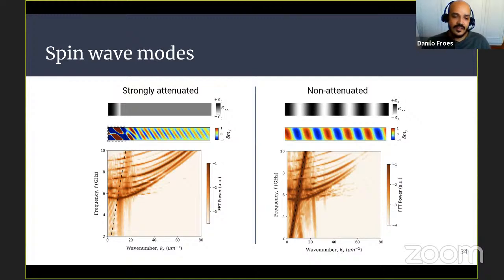Their damping is very much lower than the magnetic ones, so they propagate much more than spin waves. So we have very different behaviors. In both cases, the spin wave, the magnetic wave that's formed there, presents the same frequency as the excitation, but not the same wavelength. In the strongly attenuated case, the spin wave's wave number just follows the natural dispersion curves of the spin waves in that sample, just like we were exciting with an antenna or a coplanar waveguide.